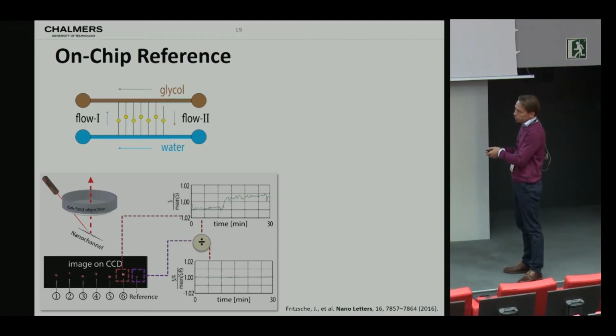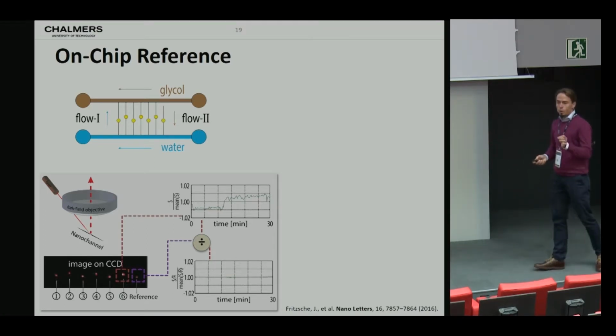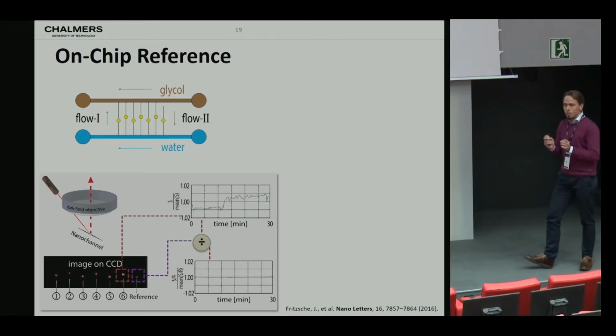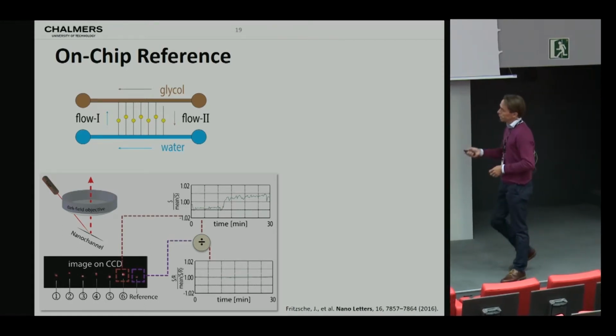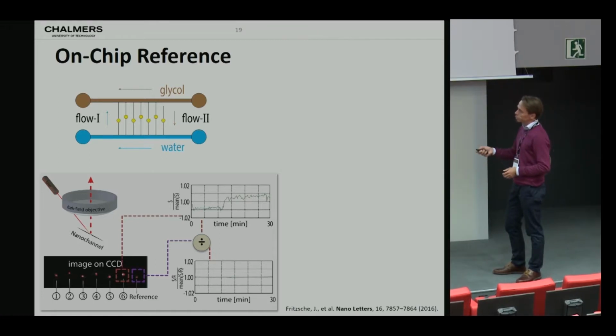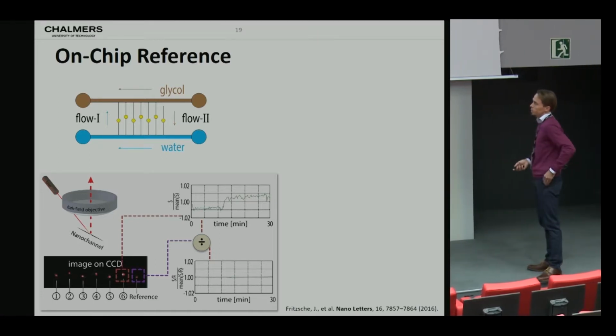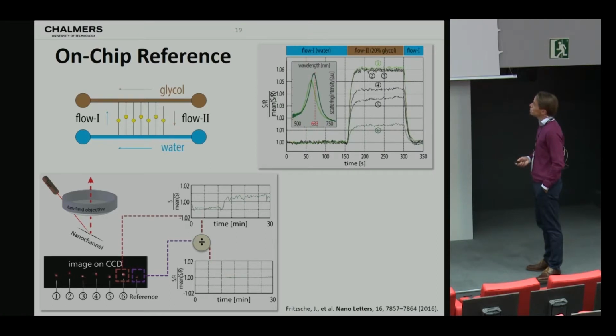One, that if you now, in the next step, want to do a sensing experiment, you can keep your reference on the chip immersed in your solvent, but you will never expose it to the analyte, because if you flow your analyte this way, this will not be immersed in analyte because you also have a flow in this direction, so you will never have any back diffusion. So we have an on-chip reference in the same medium as the one you do your experiment. And you get this very flat baseline despite using a simple, cheap helium neon laser for illumination.